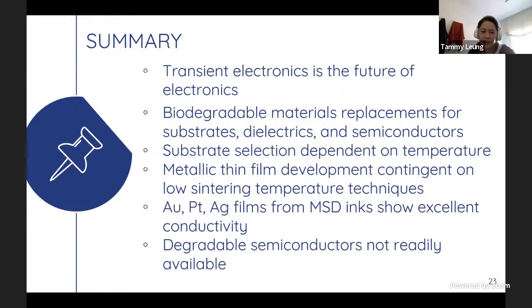We demonstrated a new type of ink called metal salt decomposition ink, where we created low temperature conductive films, such as gold, platinum, and silver with good conductivities. And unfortunately, again, because there is only a handful of semiconductors that are considered biodegradable, this is one of the last layers that we have yet to place into our devices.